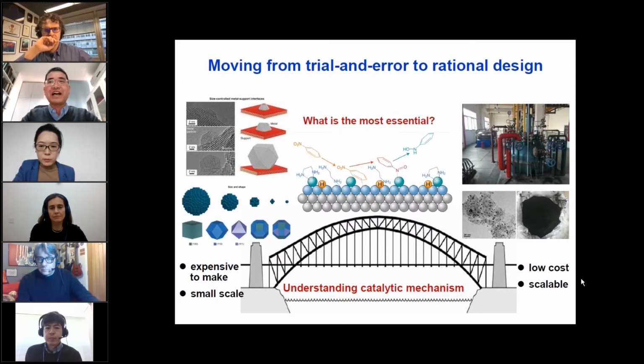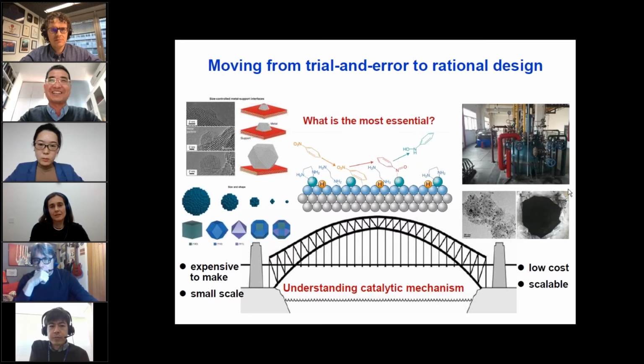So as a researcher from academia, I always believe mechanistic study is a critical step for nanocatalyst development. But of course, many of our model catalysts that we generated might not be suitable for scalable production. The main reason is that in order to get those model catalysts, in many cases, we introduce a lot of organics, surface capping agents, and use a large amount of organic solvent, which are not easily recyclable.